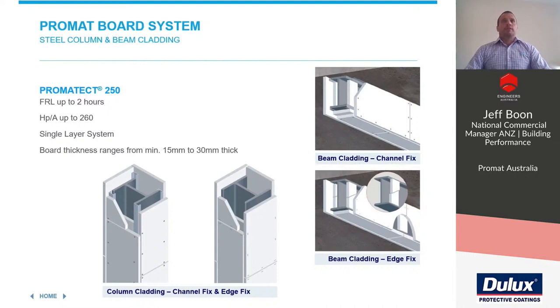The fixing detail is rather simple. Boards are butt jointed and screwed or staple fixed at 150mm centres, with cover strips located between the flanges at 600mm centres for UB and UC cladding. For SHS and RHS, boards are fixed hard up against the steel section and fixed at 150mm centres. There is no fixing to the steel section itself. Any gaps between board butt joints that are less than 2 to 3mm do not require a fire-rated seal. It is always recommended to apply a fire-rated seal where the board butts to the underside of the concrete slab.